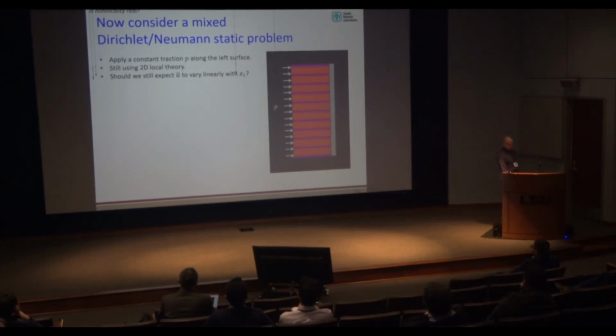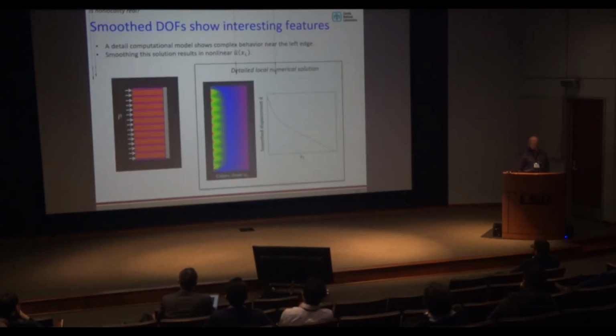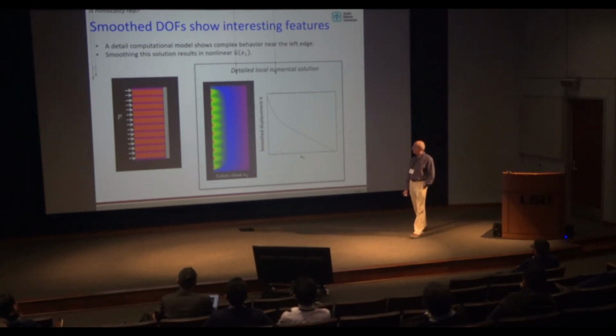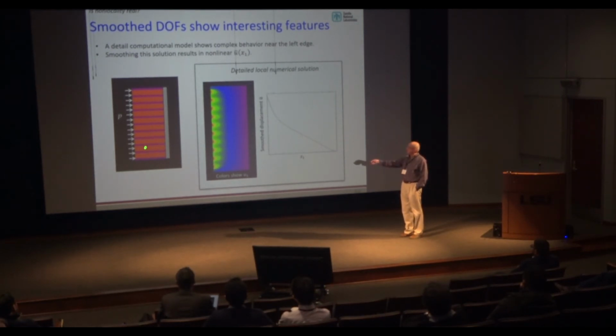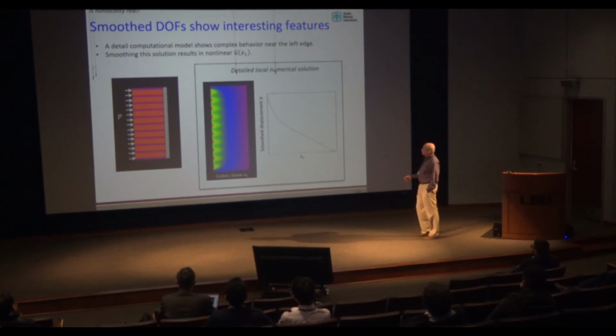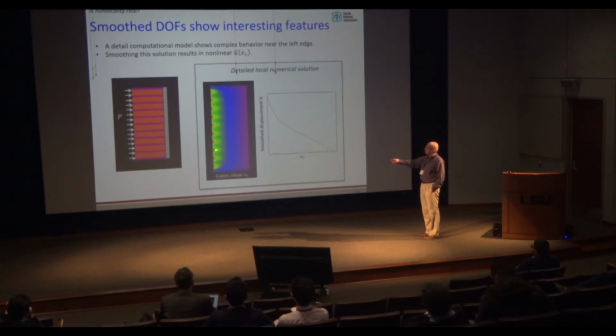Well, the local theory would say, yes, we should expect the same results if we use an effective modulus found by averaging the elastic modulus among the different constituents. But if you do the simulation in detail using the local theory and you make a plot of the displacements as a function of position, understandably, the soft material deforms more, therefore you get larger displacements there than in the stiff material.